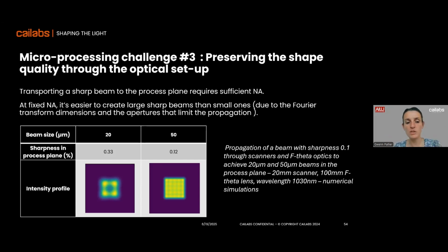In that case, we make a 20 micron beam or a 50 micron square beam, and we are using a 20 millimeter scanner, so pretty standard, and a 100 millimeter F theta lens at 1 micron. What you can see is that if your input beam has a sharpness of 0.1, meaning the transition is 10% the length of the plateau, when you are doing a very small beam, it's just cropping everywhere, and you cannot preserve that sharpness. Not only that, it's actually destroying the shape. So it's super important to pay attention to having the proper numerical aperture, depending on the size you want in your processing plane and depending on the optics you have on the optical path.